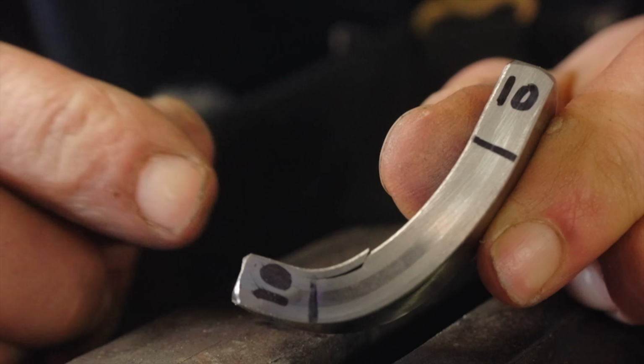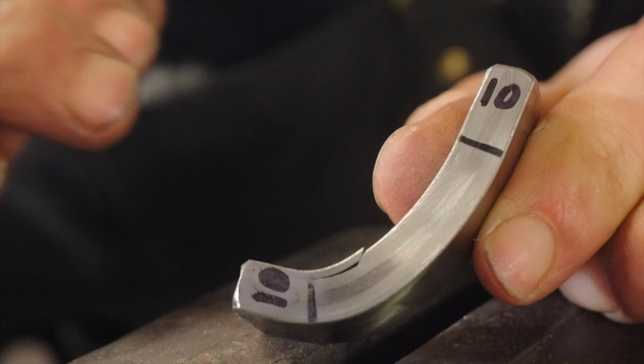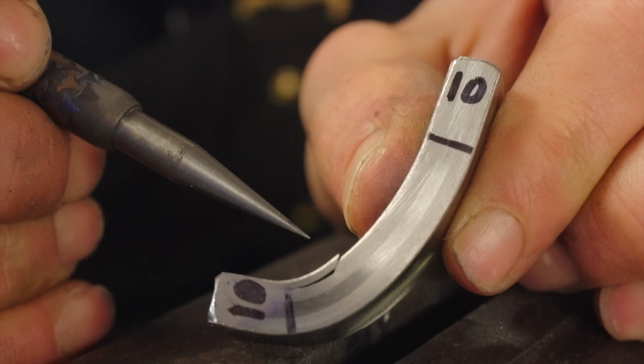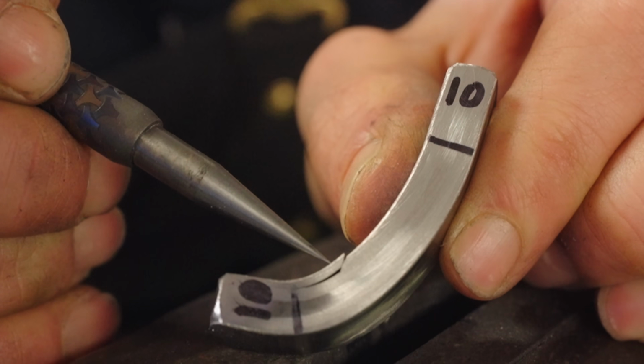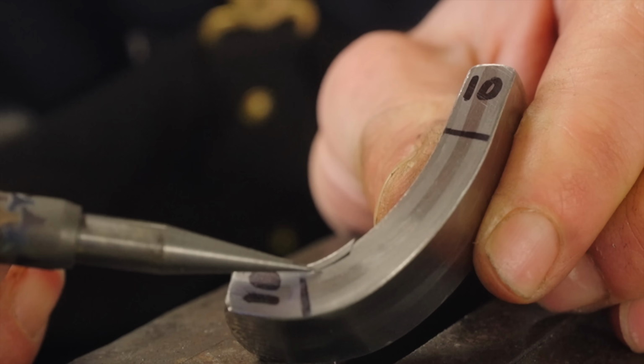Yes! It didn't break at the joint between the steel and the titanium. That is a break at the grade 5 titanium interface with the grade 2 titanium layer. And that was hard to pull. Unbelievable. I can't believe it.